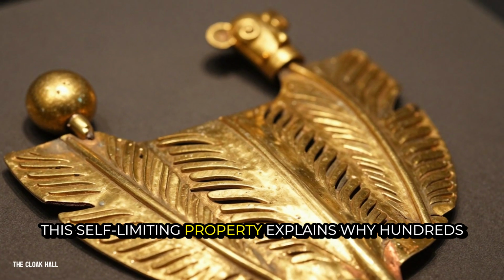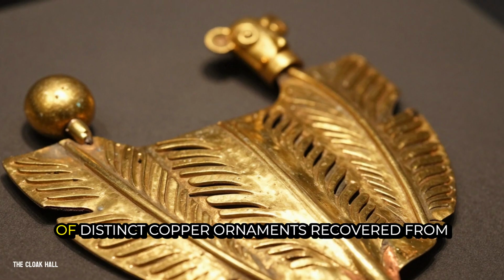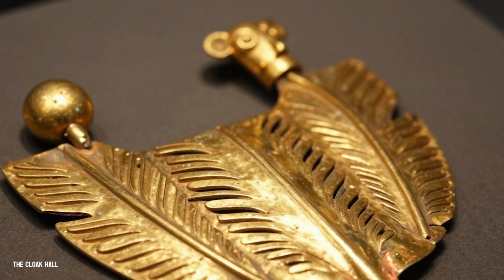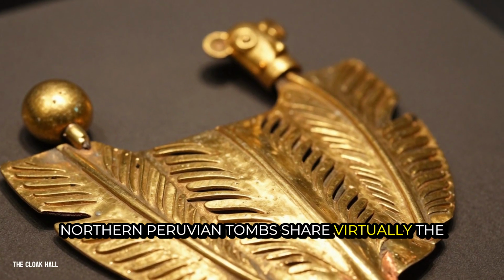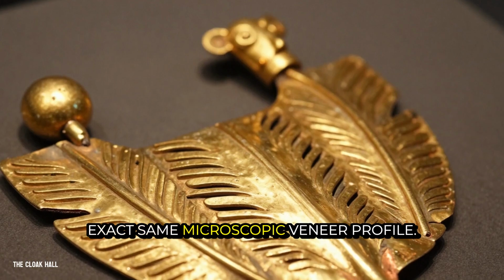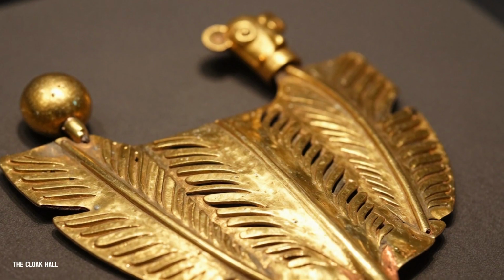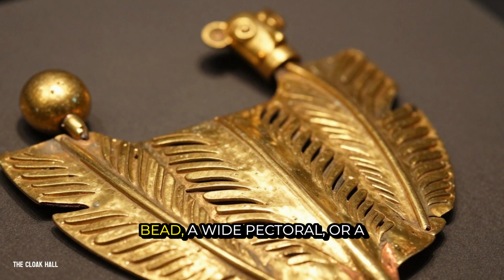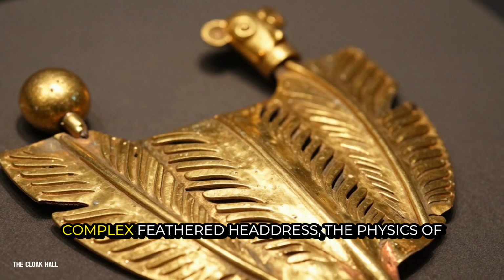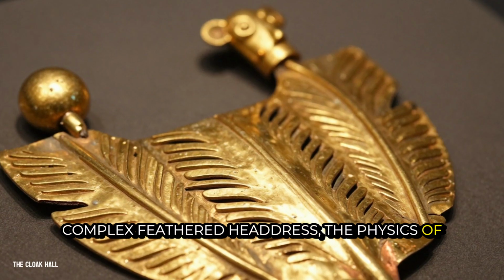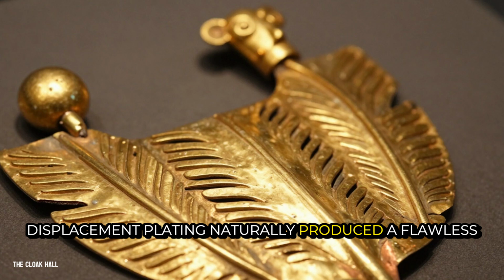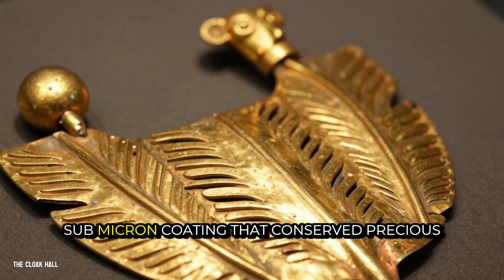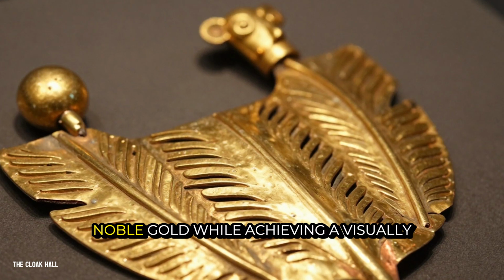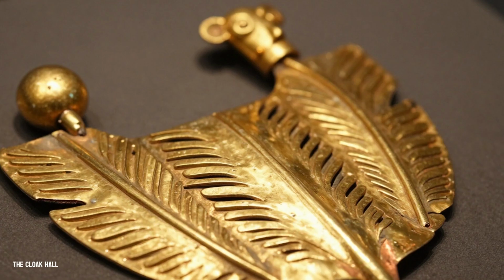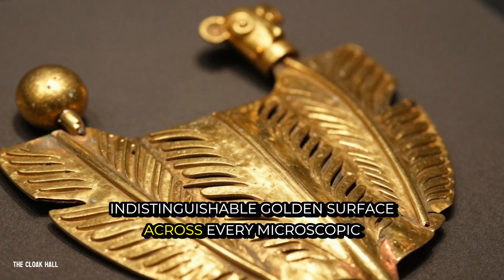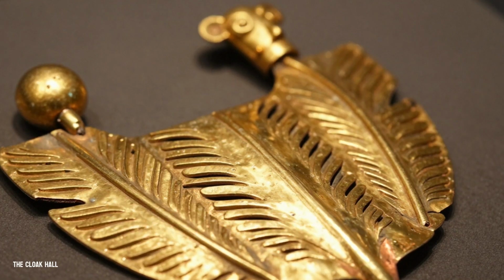This self-limiting property explains why hundreds of distinct copper ornaments recovered from northern Peruvian tombs share virtually the exact same microscopic veneer profile. Whether the object was a tiny bead, a wide pectoral, or a complex feathered headdress, the physics of displacement plating naturally produced a flawless, sub-micron coating that conserved precious noble gold while achieving a visually indistinguishable golden surface across every microscopic contour.